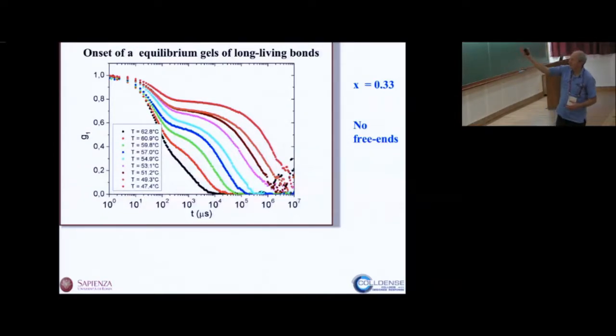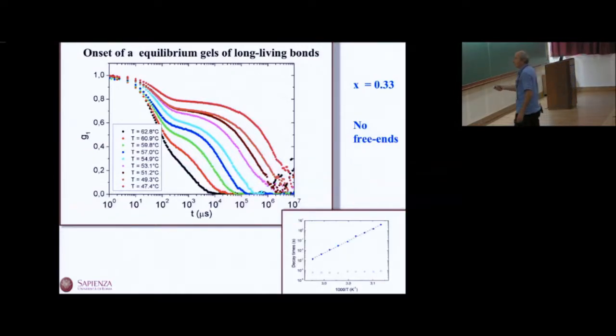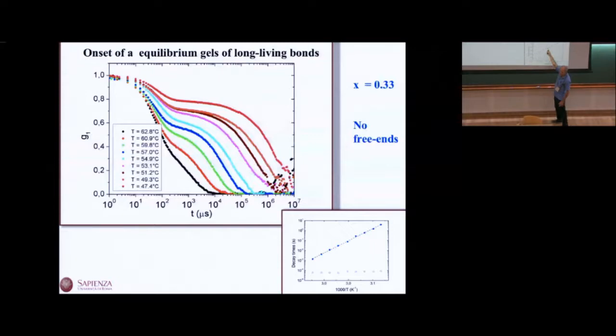It's only taking place at a higher temperature because the sticky sequence is longer. But with no free ends, there is nothing that happens. And if you look at the alpha relaxation time and you plot it as a function of 1/T, you find an Arrhenius behavior for the alpha relaxation time, like we have seen already before. The slope of this alpha relaxation time is the activation energy of the number of bases that form the bond, so as it has to be.